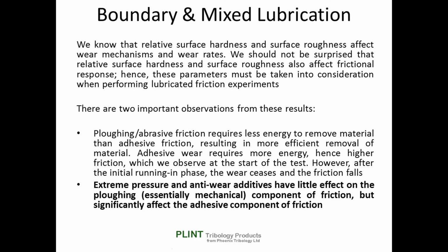The extreme pressure and anti-wear additives have little effect on the ploughing, or essentially mechanical component of friction, but significant effect on the adhesive component of friction. The results of the sliding rolling tests provide insight into what may be happening with the pure sliding tests, for example, those with a soft pin on a hard twin.